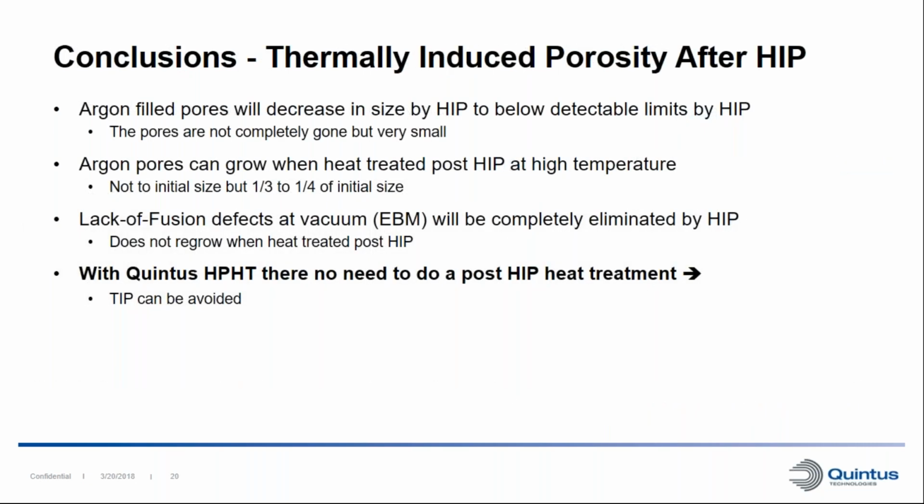So some conclusions from this paper are that the argon-filled pores will decrease in size by hipping a lot. However, they will not be completely eliminated. And argon pores can grow a little bit when we're doing post-heat treatment after hipping in a non-pressurized environment. However, they don't grow to their initial as-printed size, but to around 1/3 to 1/4 of the initial size they showed